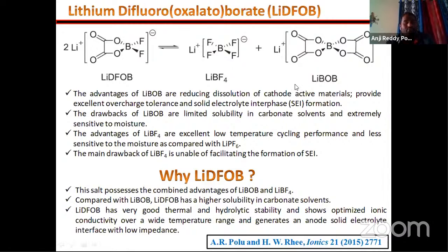Actually, LiBF4 and LiBOB are the old salts. Already many papers are available on those two salts. But the newly developed salt, LiDFOB, has the advantages of both of those salts. That's why I have chosen LiDFOB. The first point I have given here: this salt possesses the combined advantages of LiBOB and LiBF4. Compared with LiBOB, LiDFOB has a higher solubility in carbonate solvents. These are some of the advantages, and we have published that paper also.